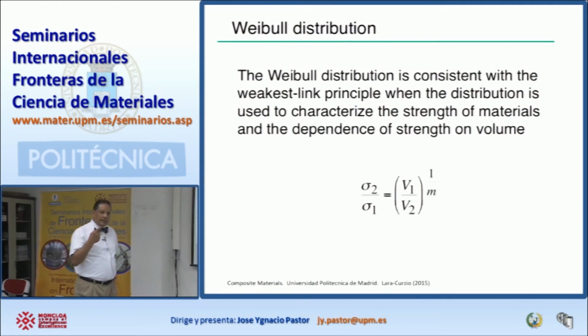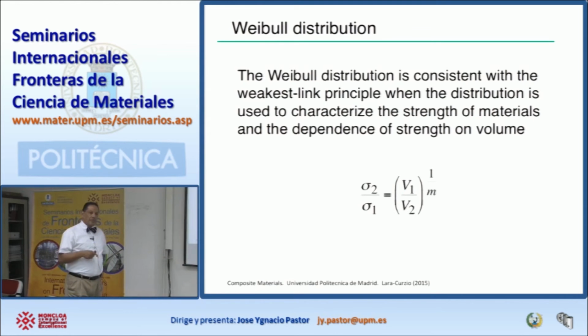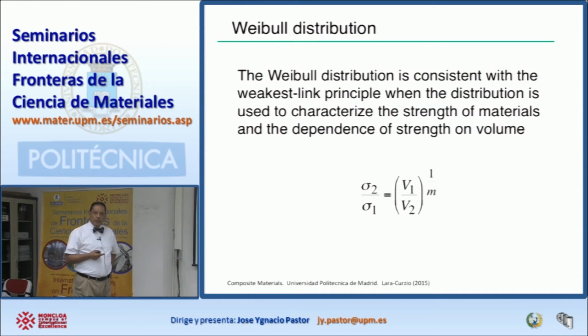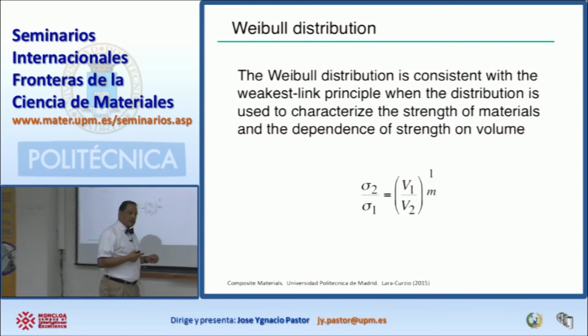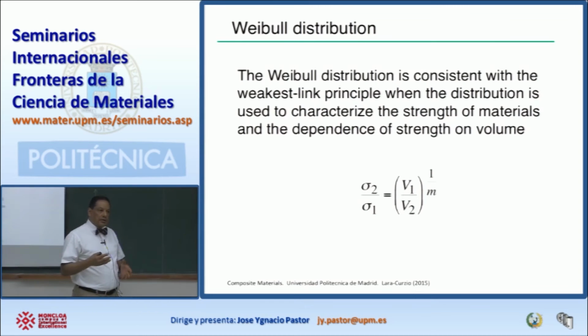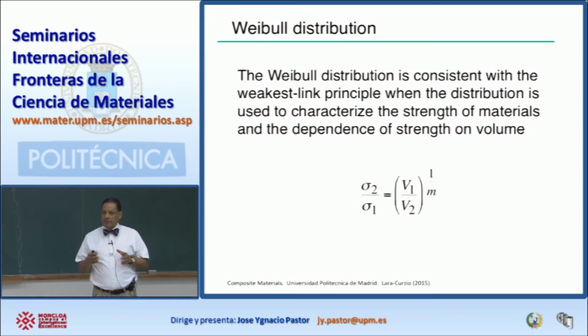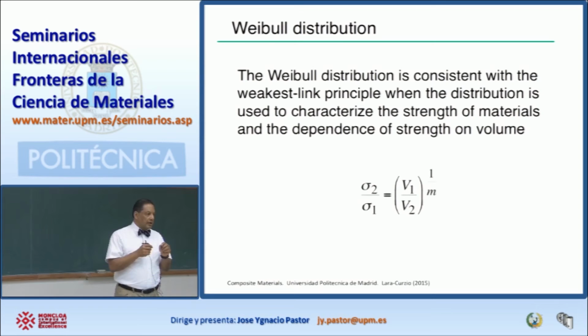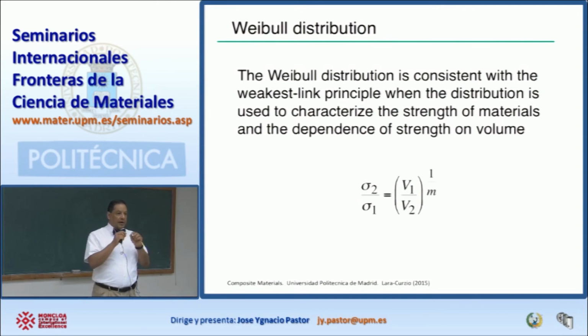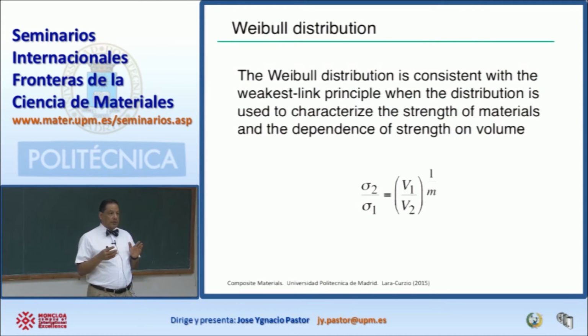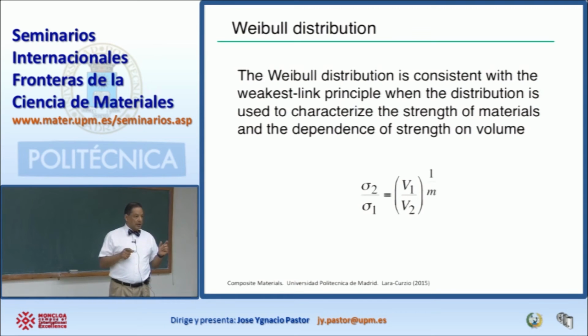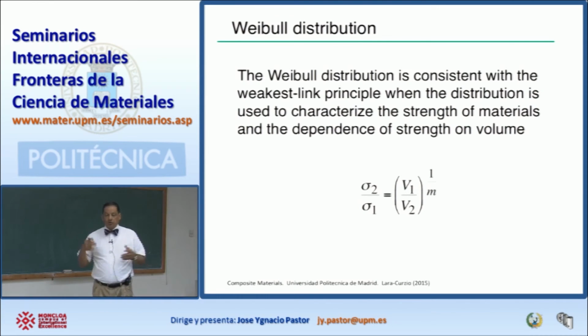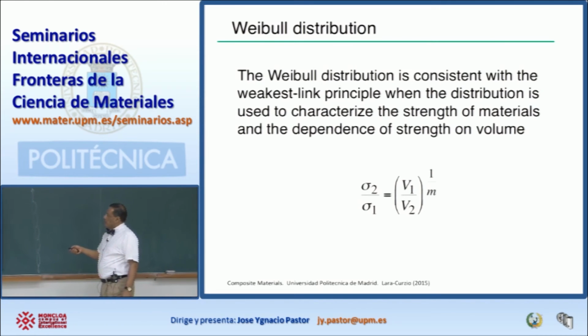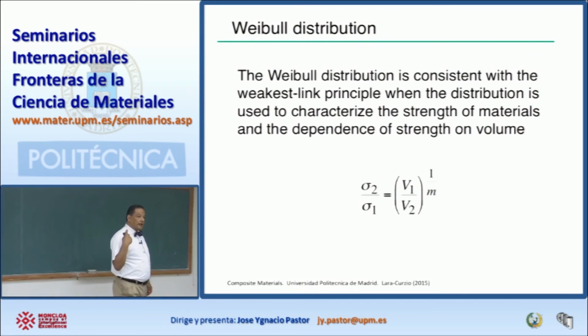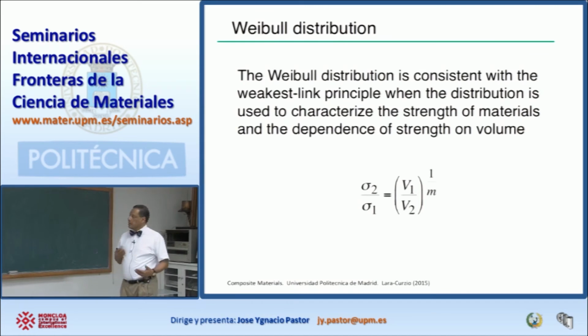And one of the consequences of the weakest link is that the strength of materials is going to be dependent on its volume. One of the consequences of the Weibull distribution is that if you have a small object, that object is going to tend to be stronger than a bigger object. Now, the idea is that the strength of materials is controlled by flaws, by defects. So let's think about a ceramic. A ceramic that has a crack is going to be weaker than a ceramic that has no cracks, okay? And that crack can control the strength. If you remember Griffith's criterion, the fracture toughness, the size of the defect, and the strength are connected. So if you have two objects, the one that has the bigger flaw is going to be weaker. And then the bigger the object, the probability of finding a larger defect is going to increase. And this is one of the consequences of the weakest link theory, that the strength of materials is going to be dependent on the volume. And that actually comes out of Weibull's distribution, okay? And that's what we know as the weakest link theory.